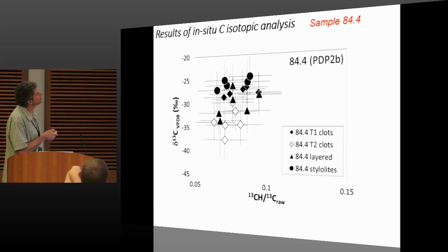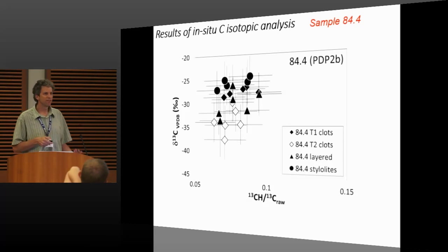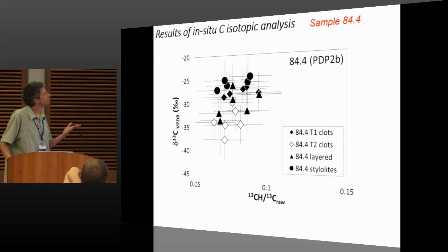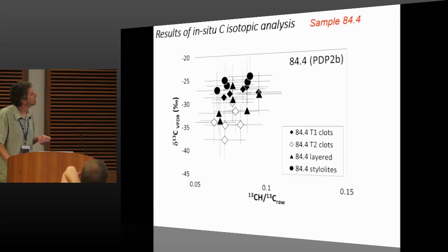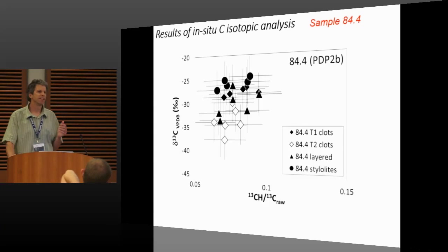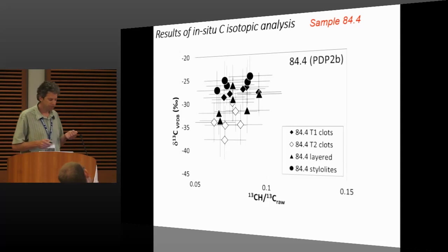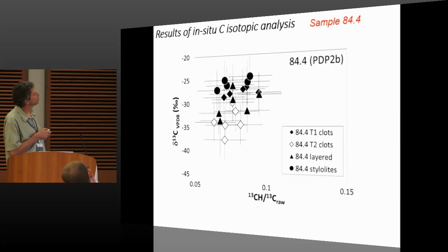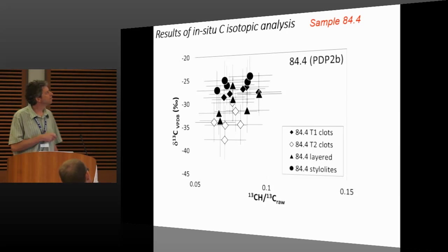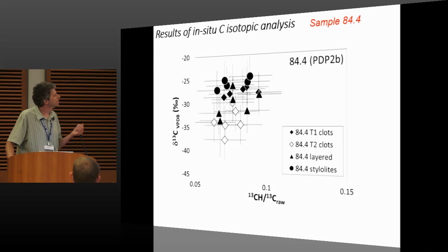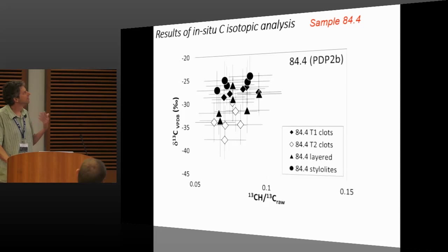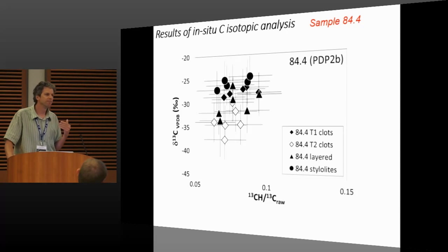First of all, it indicates that the range of isotopic composition that we see is not the result of a variable instrument bias that might arise from varying hydrogen content in the samples. And second, during thermal maturation of organic matter, it can change its isotopic composition by preferential loss of isotopically light methane. And this process usually leads to a negative correlation between isotopic composition and hydrogen-carbon ratio, which is not seen in the samples. And therefore, we interpret that the range of isotopic composition seen in the sample is an original heterogeneity and not the result of later thermal alteration.